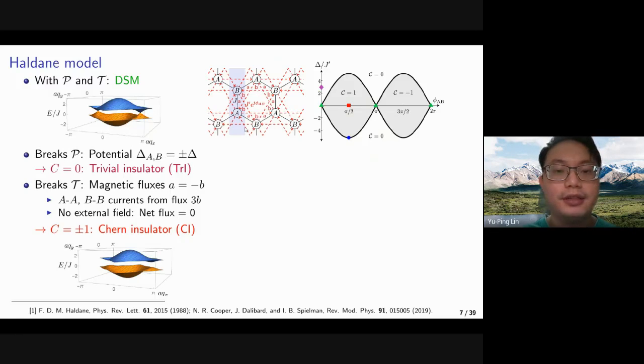However, if we look at the whole unit cell, we find that we have 6A and 6B. And because we require A is equal to negative B, the net flux through a unit cell will vanish. It means that we do not really have an external field. So we're breaking the time reversal symmetry without an external magnetic field, and it will gap out the system with a finite Chern number, so it is a Chern insulator. You can think of it as a quantum Hall effect, but without an external magnetic field, so it is also known as a quantum anomalous Hall insulator.